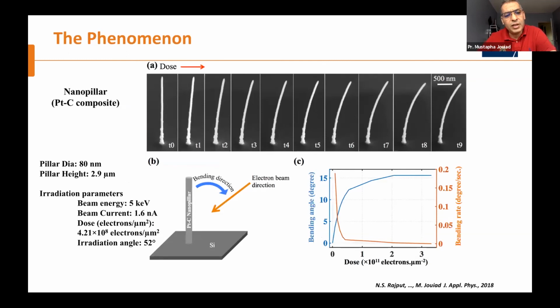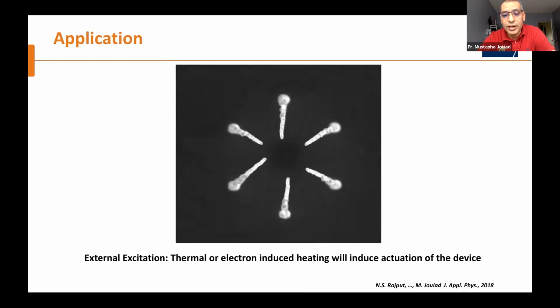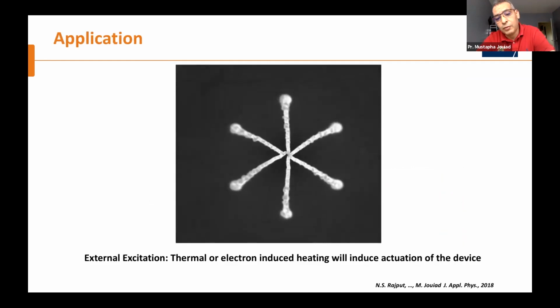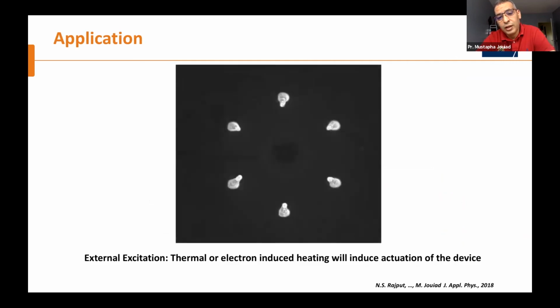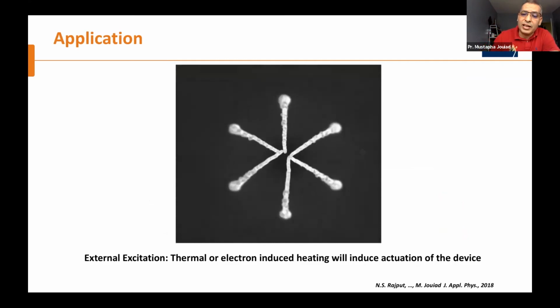Here in this image, we can show you that we produce nanopillars of Pt carbon composite, and just using electron excitation, we are able to bend them. So we were able to measure the bending energy, the excitation energy, and the bending angle. So we control the whole process of the bending, and we understand the mechanism of the bending. By doing that, we were able to make very nice nano fixtures. I can show you here, for example, nano cages that we can excite just by thermal means, and we were able to do some manipulation at nanoscale.